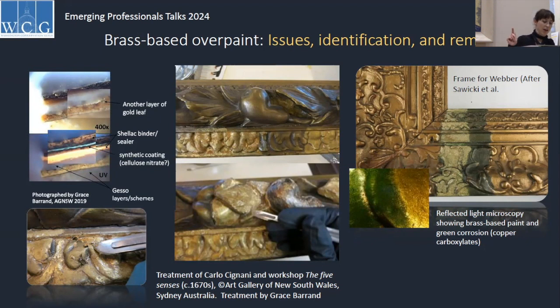And you can see up here, on the further left, this interesting green reaction product. This is carboxylate, the formation of copper soaps, which happens a lot with brass-based gilding, the brass-based leaf. It reacts with oil and synthetic binders, and that forms these metallic salts that form carboxylates, and that results in green corrosion products. Once that happens, it's irreversible, irretrievable, and you need to remove that and replace that gilding.